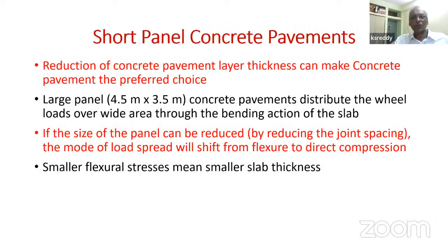Suppose you want to reduce the thickness of the concrete slab. Large panels will be subjected to more flexural stresses, more curling stresses, so you will not be able to reduce the thickness significantly. Typically, we used to have thicknesses of the order of 330 millimeter, 270 millimeter, 250 millimeter. But if you can reduce the size of the panel to 1 meter by 1 meter, or 1.5 by 1.5 meter, you are reducing flexural stresses, and maybe converting to more of direct compressive stresses on the foundation layers. So it would be possible for you to reduce the thickness of the slab.